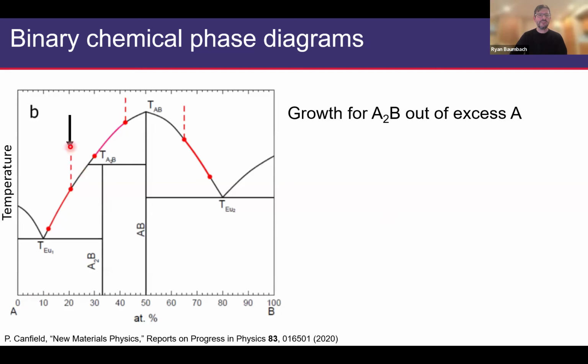All right, so if we're in excess A, we're going to be where this black arrow is. If we heat this combination up into the melt and then slowly decrease temperature and cross this phase boundary, what's going to happen is that because it's connected by this horizontal boundary, we'll begin to drop out this A2B from the melt. If we do it slowly enough, it'll form single crystals as it comes out. Also, we'll be depleting the melt of B, so we'll be moving to the left here. The melting temperature will lower, and as long as we're slowly decreasing temperature and we don't exceed this eutectic point, we're going to be able to continue to form this phase directly out of the melt.